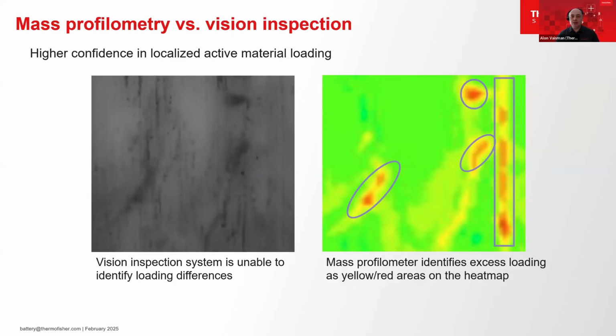The example in this slide is a good way to consider the difference between optical inspection and mass profilometry. The image from an optical inspection system on the left looks at the surface of the electrode, and in this case, the algorithm did not flag any abnormalities. Mass profilometry mapping of the same sample shows clearly that the darker areas in the image are actually areas where the loading is too high, indicated in red. Additionally, the vertical streak of high loading, most likely resulting from an incorrect adjustment of the die bolt in the coater machine, is clearly identified by the mass profilometer, while it is completely invisible to the vision inspection system.